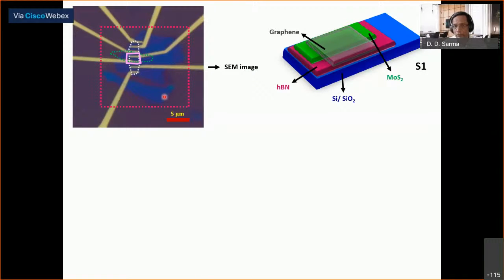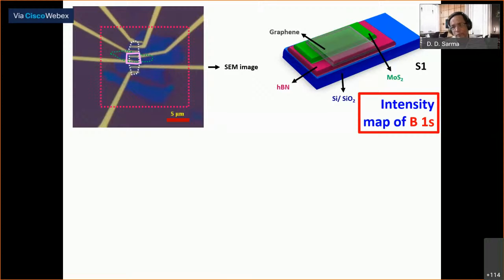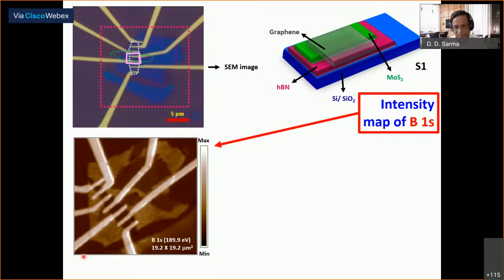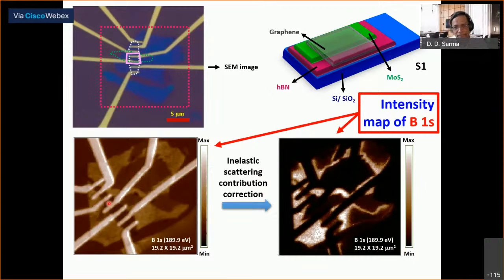Using the spectromicroscopy, because you are elemental sensitive, I can map out what is the element where the intensity of boron 1s is, and when I do that, I see this. You can see the lead still, but lead has no boron. It's actually an artifact because I'm not correcting for the background contribution. So if I measure only the peak intensity, subtracting out the background, which I'll do now, then I get rid of these and I see exactly where boron is spread.